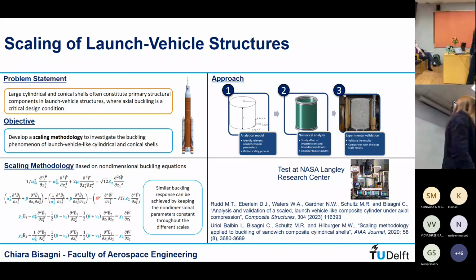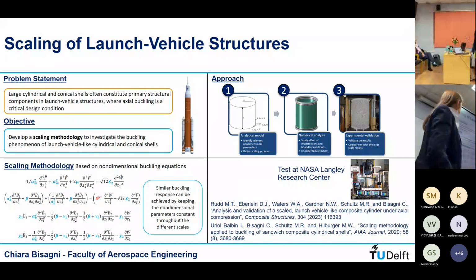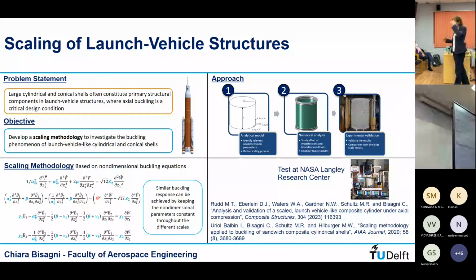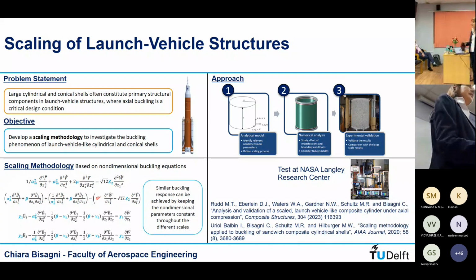So this is about the scaling of the structures. We develop a methodology to scale the large structures analytically, based on non-dimensional buckling equation. And from that, we also built the numerical model, and at NASA, they manufactured the reduced shell structures. Some tests were done in September, some tests were done before COVID. And we tested them, and so we had the experimental result, to see the correlation between experimental, numerical, and analytical, but also between this smaller scale to the real scale of the larger structures.